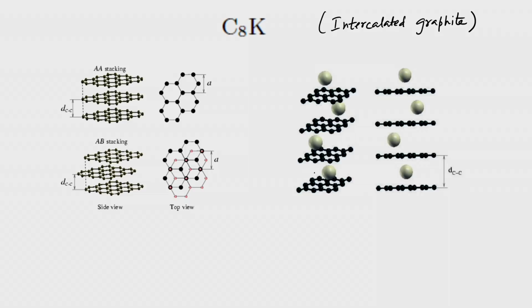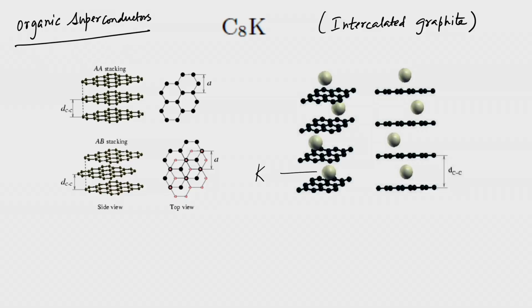are the potassium, which is represented by K. It has a nice structure, like a serpentine structure. So, this is the intercalated graphite, and it actually showed superconductivity below 1 Kelvin. So, this is an organic superconductor. Let us write that these are organic superconductors, and Tc is just about 1 Kelvin. So, it is a small transition temperature.